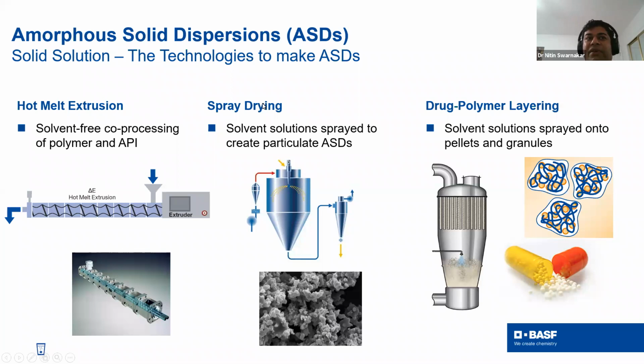But if you look at spray drying technology, it is also a good technology, but you need some kind of solvent. For example, you need ethanol or methanol, which generally dissolve the drug and polymer, and then you spray them and collect in one chamber. So this is pretty much spray drying. So basically spray and drying.